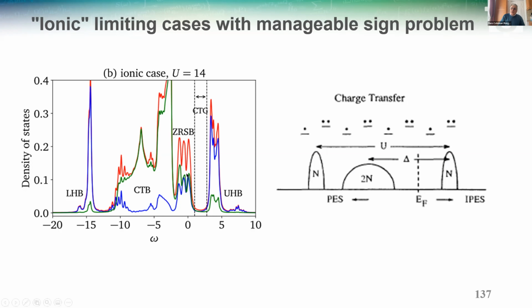Okay. What has been recently proven is that the asymmetry between electron and hole doped cuprates doesn't come out right in the Hubbard model. And the latest DMRG results show that actually the ground state in most of the Hubbard model, especially on the hole doped side, is not superconducting, it's all stripes. So the ground state is actually wrong if you do it with the best quantum mechanics calculations currently.